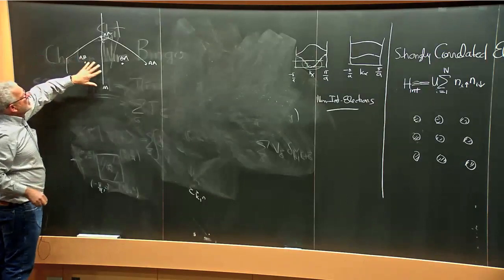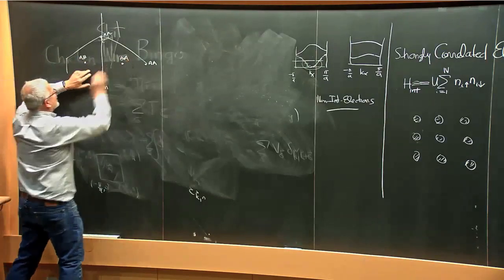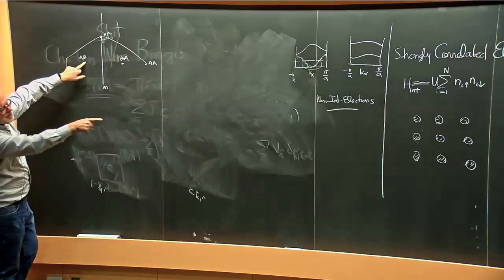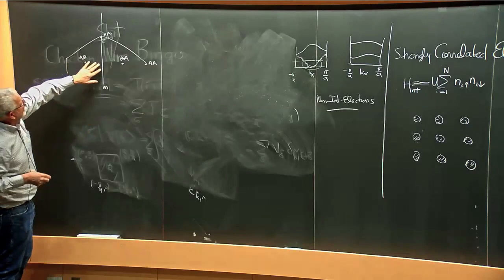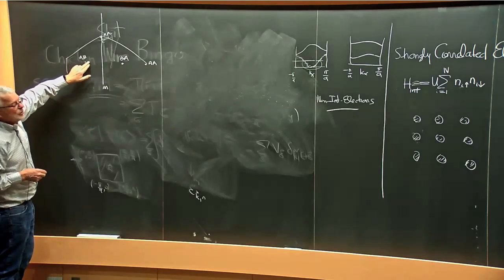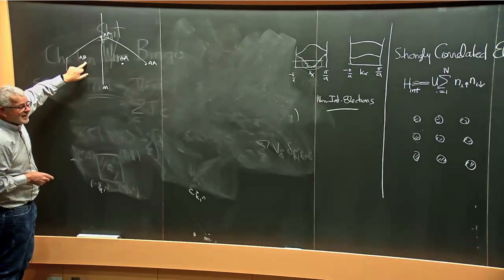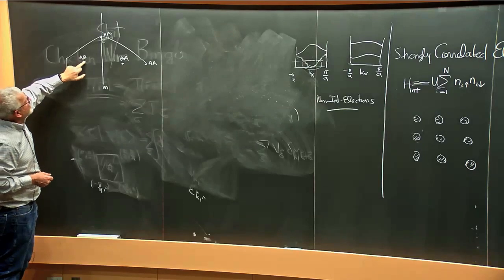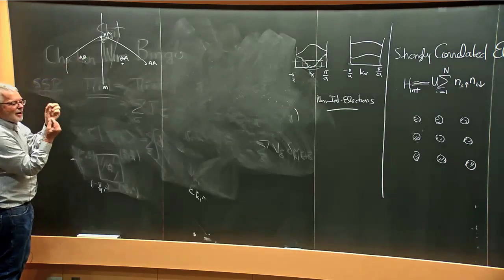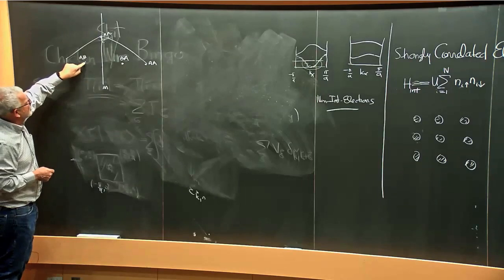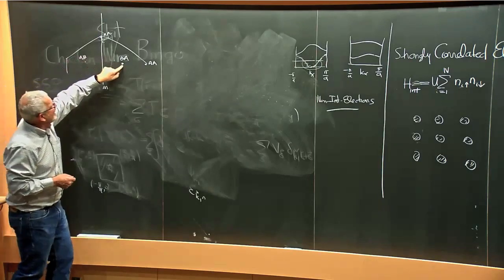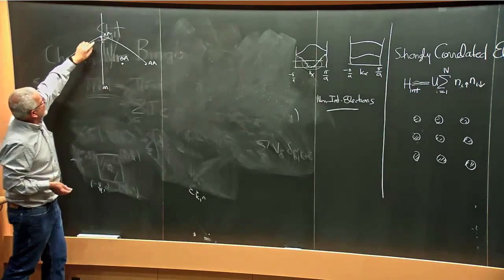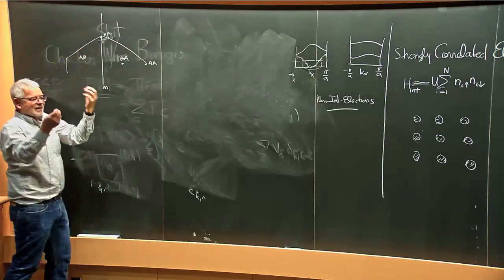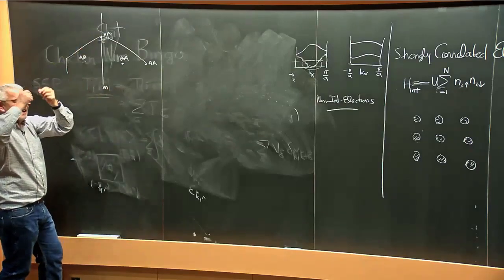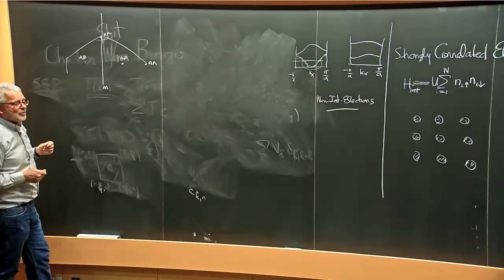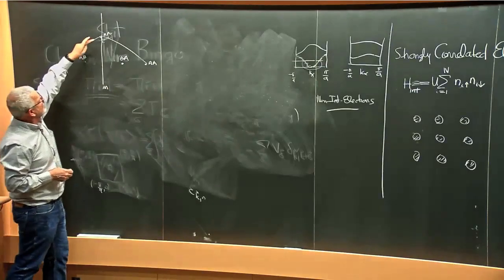So in the Moiré pattern, we go from places with the band structure on the left there. It turns out there are two band crossings at the same momentum. The two band crossings of the two layers become degenerate in momentum space here and here, whereas at these AA points, there's actually a whole ring of points in momentum space where the two bands cross. That's a very singular limit.